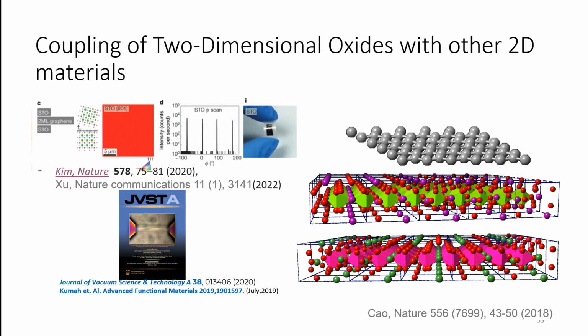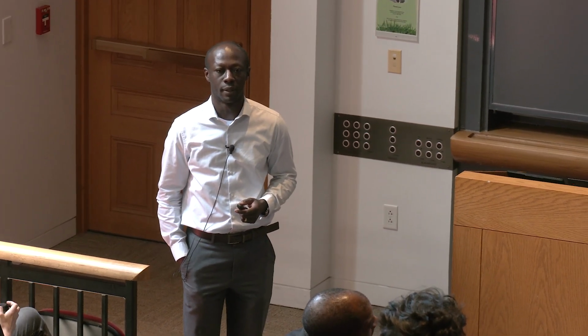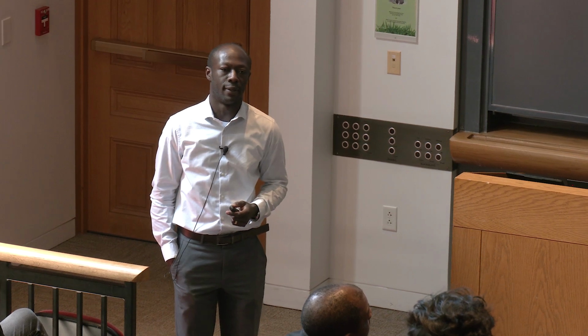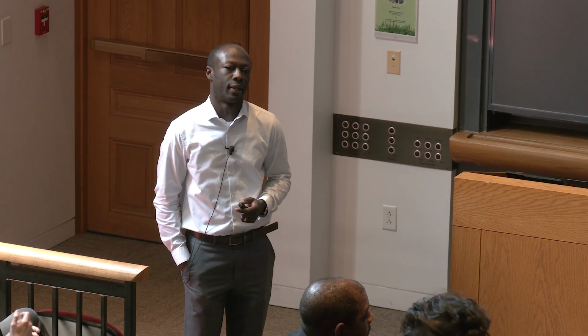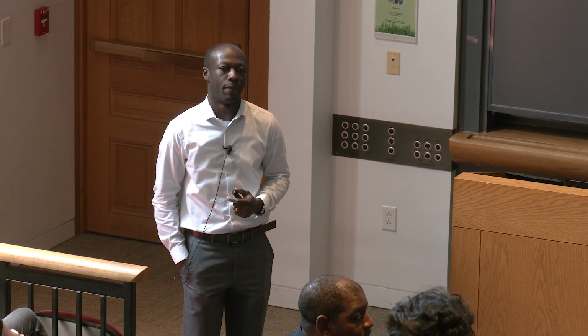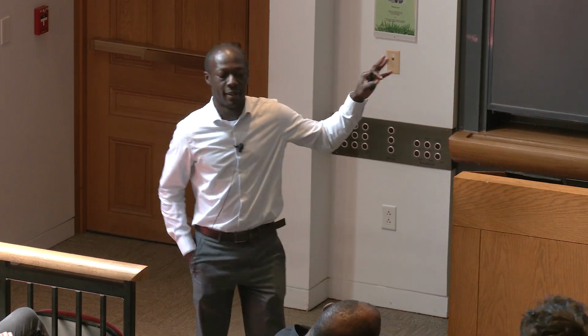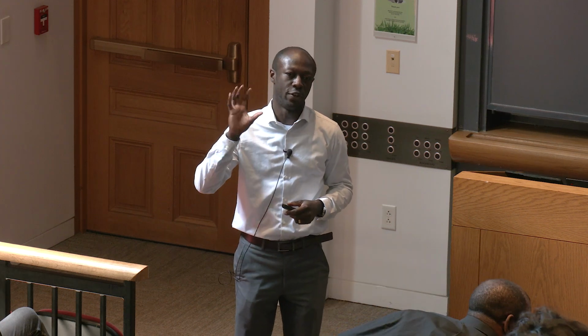Thank you. I know it's a bit unrelated, but seeing how you can change whether it's polar and it's a polar metal, do you realize optical phonons in this, like strong optical phonon coupling? Is there a Reststrahlen band, and can you actually utilize that, like turn on and off interesting optical properties? That's a very good question. We've not done it for this system, but there's quite a bit of work being done in these oxide systems where they're actually trying to use light to induce both electronic changes and structural changes, which will change what the phonons look like. But yeah, the fact that it's polar means that we have that coupling we can think about playing around with. Right. So you can actually turn on and off the Reststrahlen then. Right. Potentially. Yes.